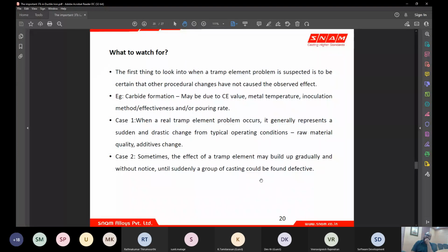So there are two cases. In case one, there is a real tramp element problem. It generally comes suddenly. Say for example, there is a sudden change in the scrap material which we have bought, and there is an influx of such new scrap coming into your melting, and that goes into your production, and you get liquid metal and you pour ductile iron castings, and because of a sudden change in the raw material, it would have led to a rejection in the casting. It can be one of the cases, it need not be every time, and there need not be a trend in such kind of rejection.